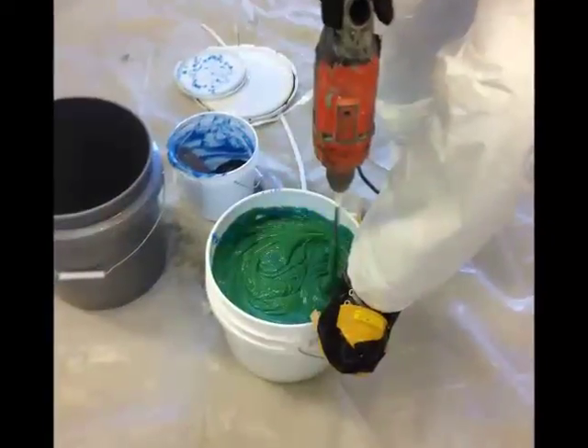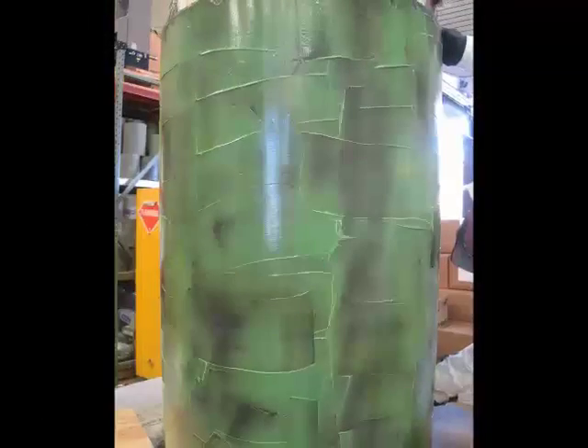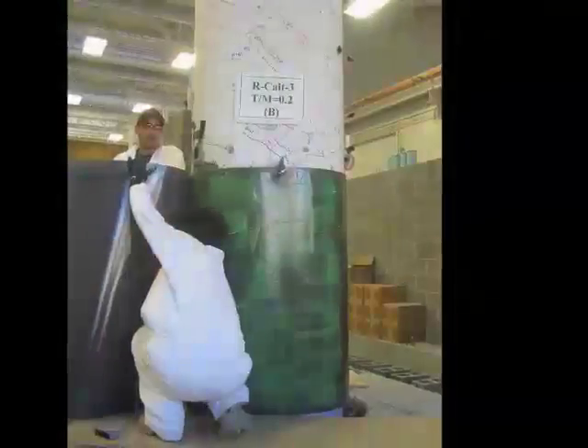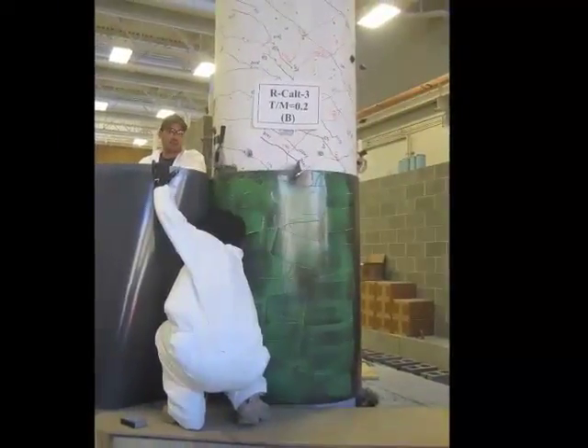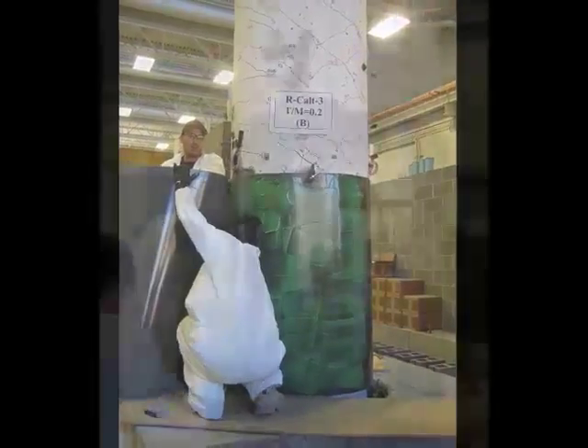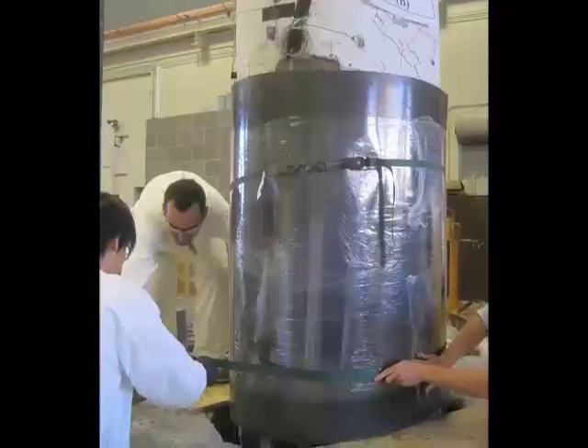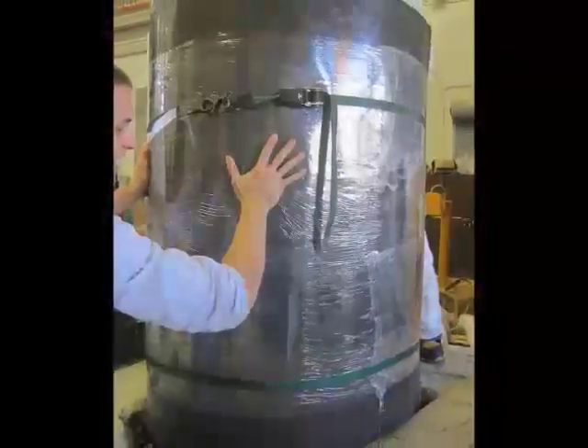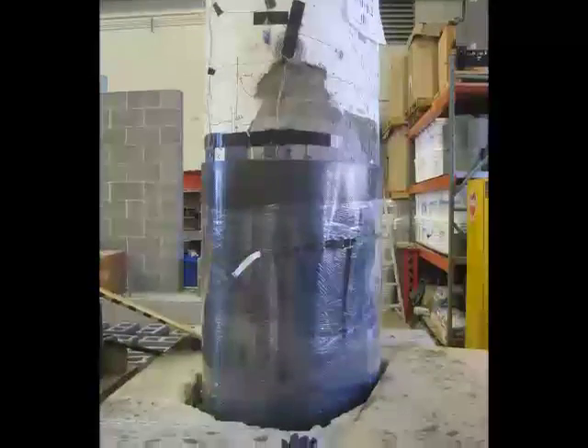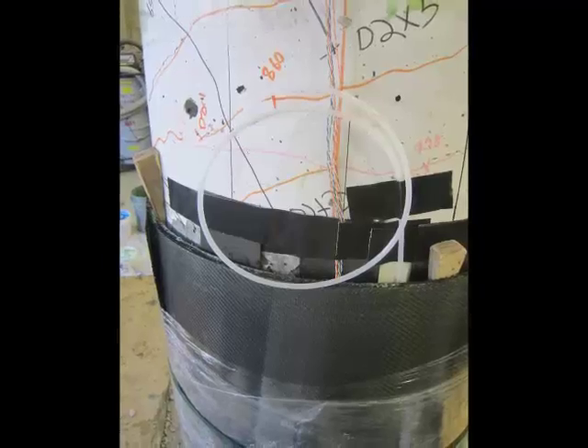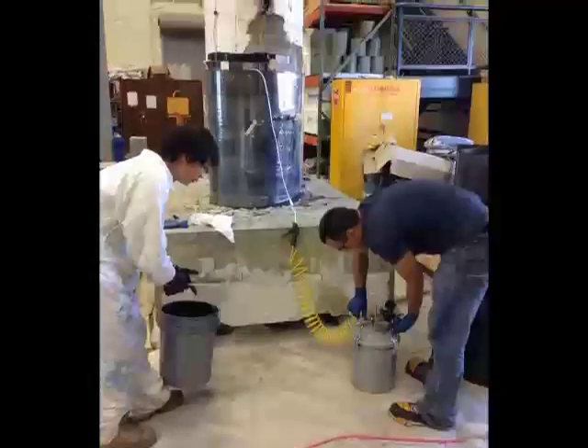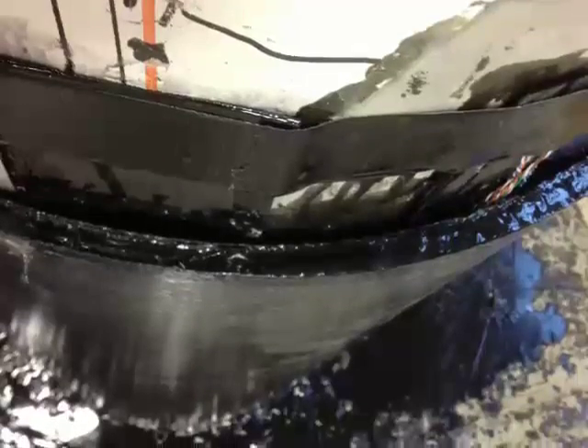QuakeBond J201TC tack coat was mixed and applied to the surface of PileMedic PLC 100.60 carbon laminate. The PileMedic laminate was tightly wrapped around the column, creating a 4-foot-tall, 7-ply thick jacket with a total thickness of approximately 0.3 inches. The jacket can be temporarily held together using shrink wrap or ratchet straps. The PileMedic jacket was then pushed down about 10 inches into the cut trench. QuakeBond 320LV low-viscosity resin was mixed and blended with aggregate and placed to fill the trench. Using the previously positioned plastic tubes, QuakeBond 320LV low-viscosity resin was mixed and pumped into the annular space. This bonded the carbon strips, the concrete column, and the PileMedic jacket together so they could resist the applied load simultaneously.